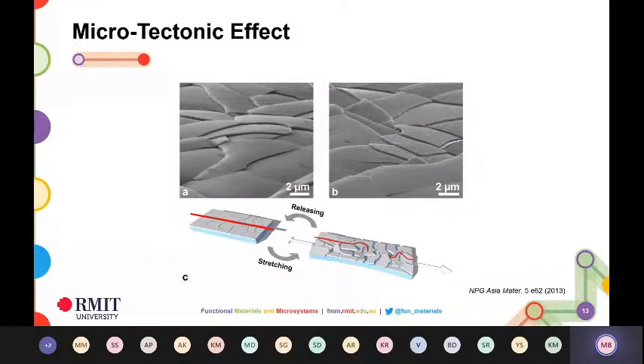And when we took a look at these materials in the microscope, we saw that it was no longer a thin film. So it's not that it's a thin film which has cracks. Now, normally, if you put gold metal films on PDMS, you will see you have just a cracked film at the end of it. This is not cracked. This is more like a plate-like structure. So it's like overlapping plates sitting on top of each other.